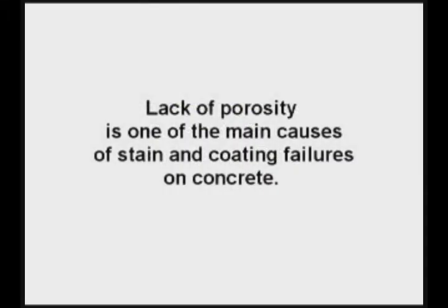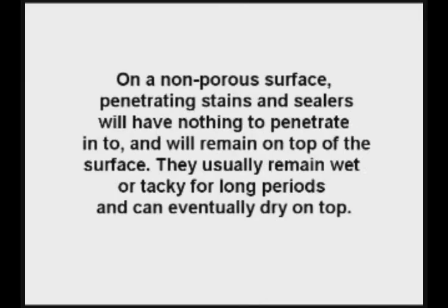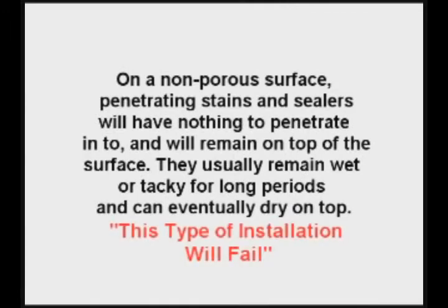Lack of porosity is one of the main causes of stain and coating failures on concrete. Porosity equals voids or open space. On a non-porous surface, penetrating stains and sealers will have nothing to penetrate into and will remain on top of the surface. They usually remain wet or tacky for long periods and can eventually dry on top.